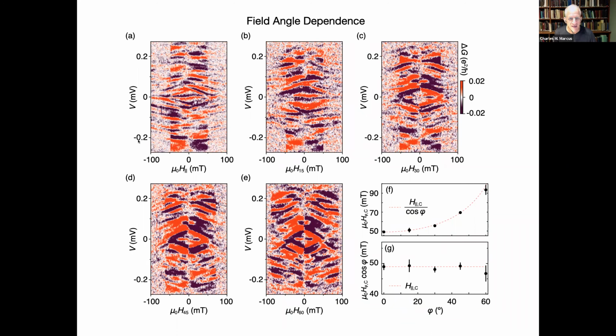Well, when the magnetic field is along the wire, it looks like about 50 millitesla in this particular wire, some wires a little more, some wires a little less, was where the hysteresis window closed. And now the two traces were on top of each other. Then you come back, the hysteresis window opens, this one has its coercive field, the other one has its coercive field going up. And over about a 50 millitesla window is this coercive field opened.